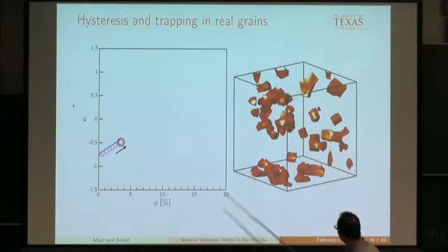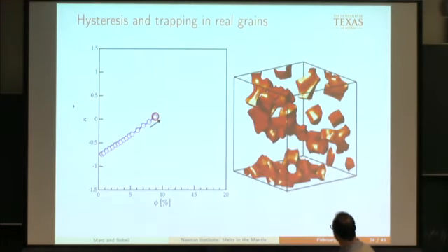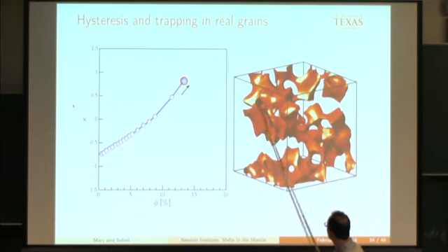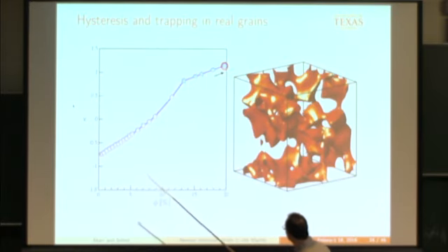And so we're increasing it. What you want to imagine is essentially this material is melting, melting, melting. The pockets grow larger, they're not connected. And we're just showing a cutout of the medium, right? It may look connected here, but it's not. And then eventually here, at somewhere around 14%, now it's clearly connected. You have big fat tubes. And you see there's a break in the evolution of the curvature as you melt it further.